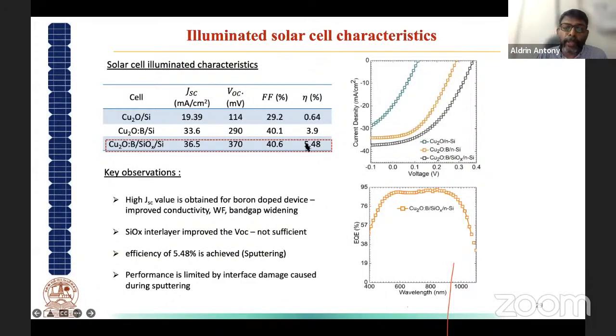And then further, to improve that, we put a silicon oxide in between by a natural process, like if you expose the silicon by dipping it in a hot nitric acid, it forms a silicon oxide on the surface. And then we did this copper boron oxide deposition over the top. And the silicon oxide helps in giving a better passivation. And that passivation helps to improve the open circuit voltage from 290 to 370. So this was our first report on this copper boron oxide used as a carrier selective layer. Or this is even the first report of a P-type material, copper boron oxide, and its application in a carrier selective solar cell with the silicon.